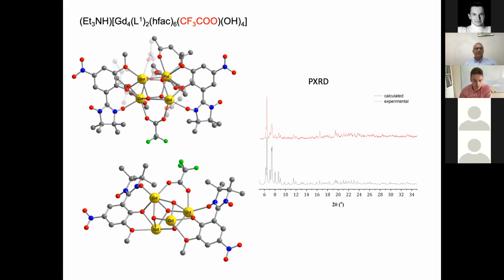We also checked the ability of this ligand to generate 2p4f complexes. And since we observe a degradation of the hexafluoroacetylacetonate ligand during the synthesis, a well-known situation, resulting in trifluoroacetate ligands, we checked the purity of the crystalline phases by powder X-ray diffraction, just to be sure that even if we observe this decomposition of the ligand, we have pure crystalline compounds.